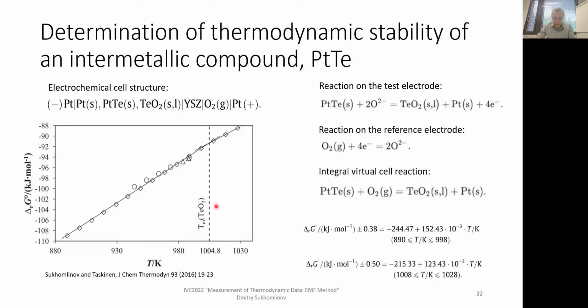So, the dashed line on the graph shows the melting temperature of tellurium dioxide. Most of the data points were measured below it and just a few points above. And then we have 2 temperature ranges, with 2 different delta G of reaction expressions for each of these lines. And they cross at the melting temperature of tellurium dioxide.